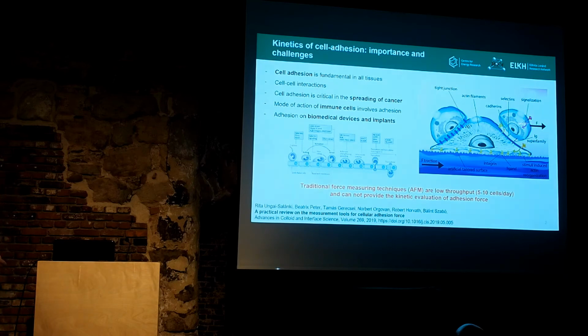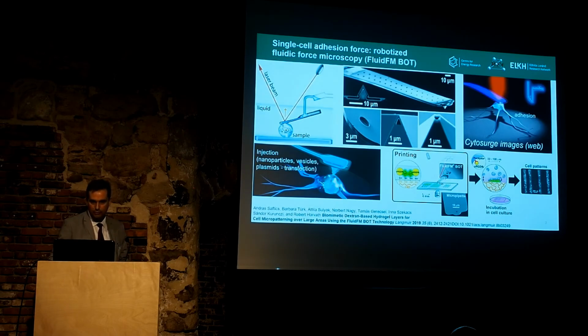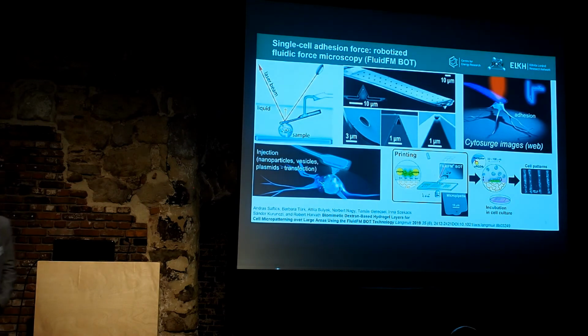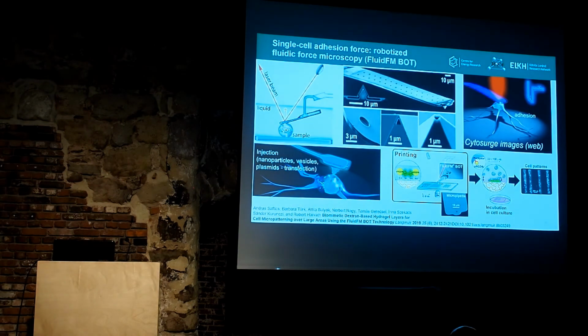And we have to measure this adhesion, and especially the force of these adhesions. This is quite challenging, especially at the single cell level, because one should measure force in the nanonewton, piconewton range with very high precision. And with traditional techniques, the throughput is extremely low. For example, with AFM, one can measure 5-10 adhesion events per day, because it takes so long to perform one experiment. And we would like to speed this up significantly, and our aim is not only to speed this up and increase the throughput of adhesion measurements, but to measure the adhesion events in real time.